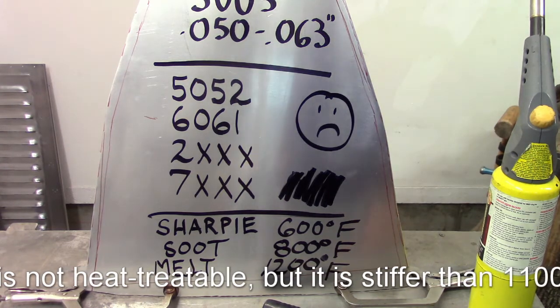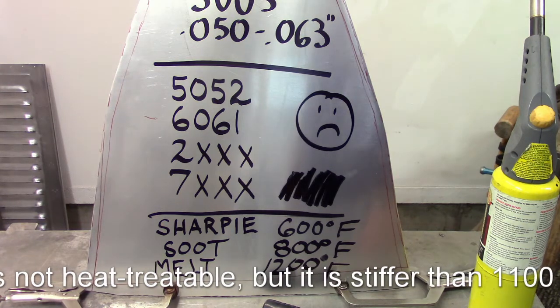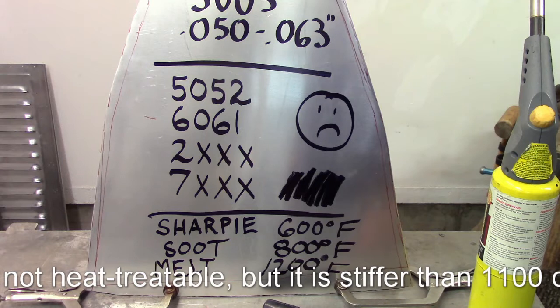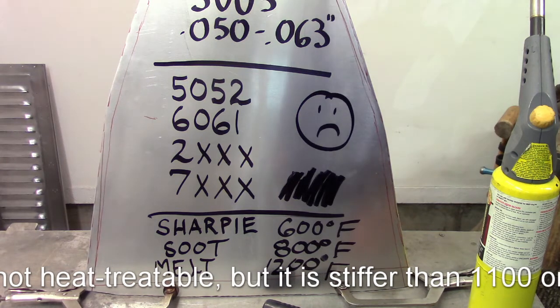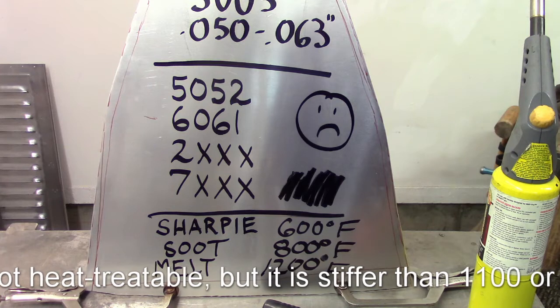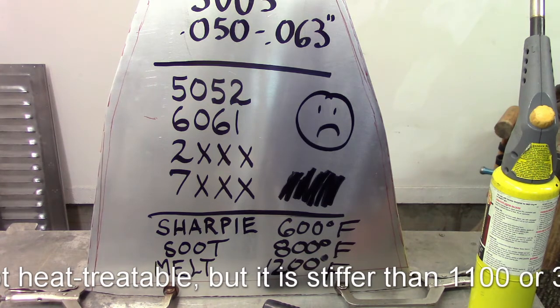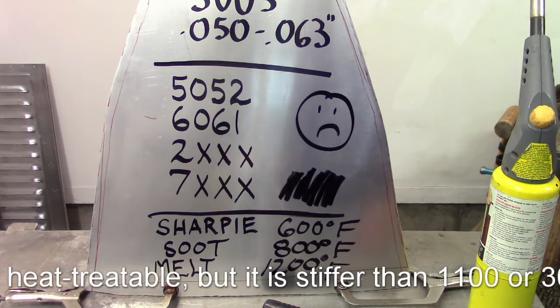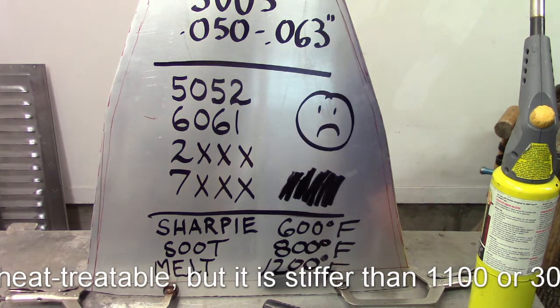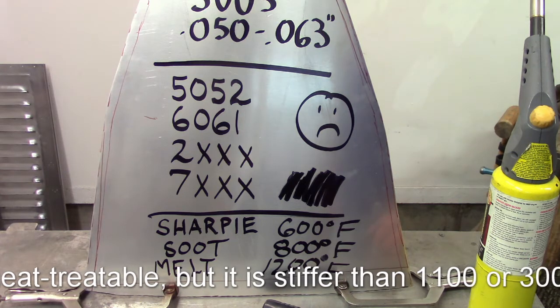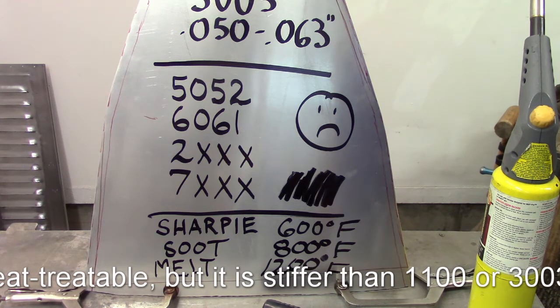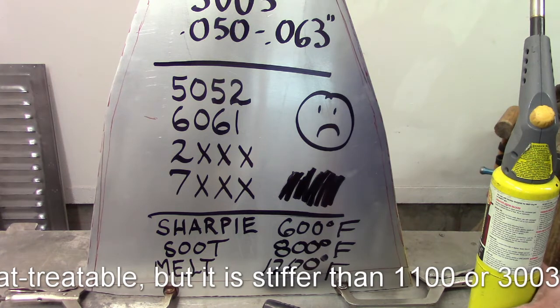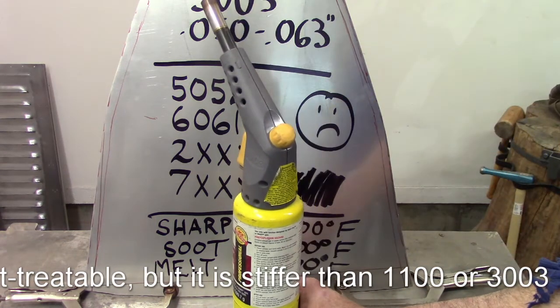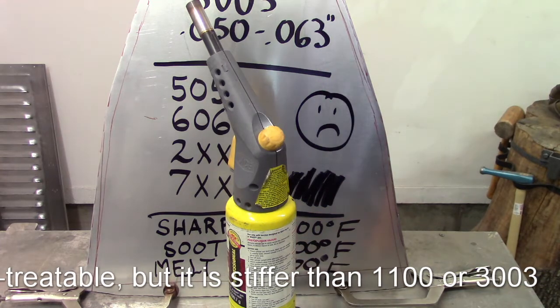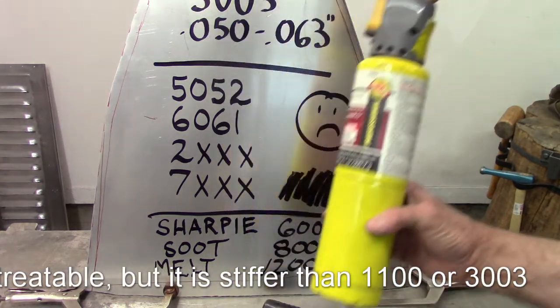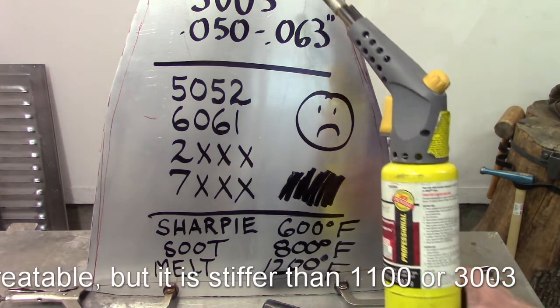Another commonly used method is to cover the material with acetylene soot and burn that off. It burns off at 800 degrees. The metal will be a little bit softer than the Sharpie method, but there is some risk involved because the aluminum itself starts to melt around 1200 degrees, so it's pretty easy to go overboard if you've not done that before. If you don't happen to have an oxyacetylene torch, you can still use a MAP gas cylinder like this. You can identify MAP gas by the yellow color of the cylinder.